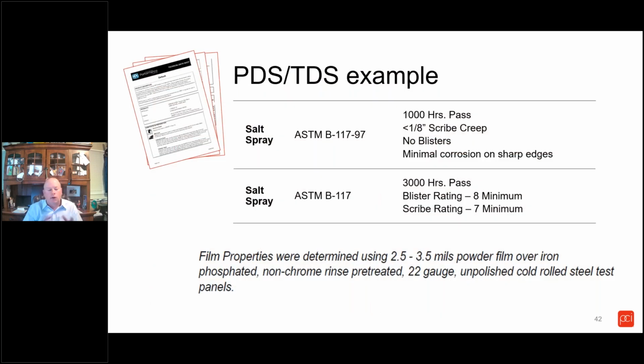So when you look at the TDS from your powder supplier, you may see a corrosion rating of 1,000 hours, but it should also dictate what is pass and fail. In the first example, you have an 1/8 inch creep, a little more than 3 millimeters from the scribe, no blisters, and minimal corrosion on the edges.